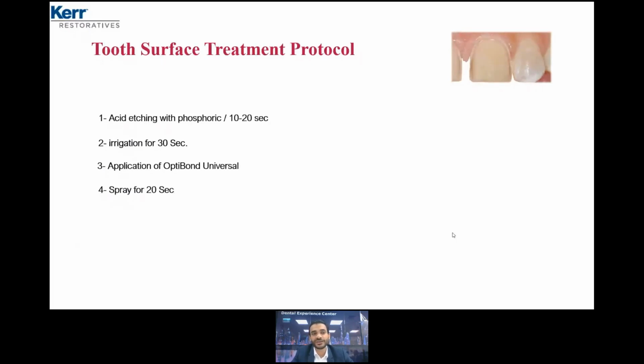But why do we need to use phosphoric acid first? Because we are in enamel. And because we are in enamel, we have a high mineralization. So we need first to add phosphoric acid, only phosphoric acid, to have the highest etching power, in order to clean and to create porosity in the enamel, remove the smear layer, and also to open the dentinal tubules. So it's better to start with acid etch with phosphoric acid in the treatment of the tooth structure, especially if we are on enamel.